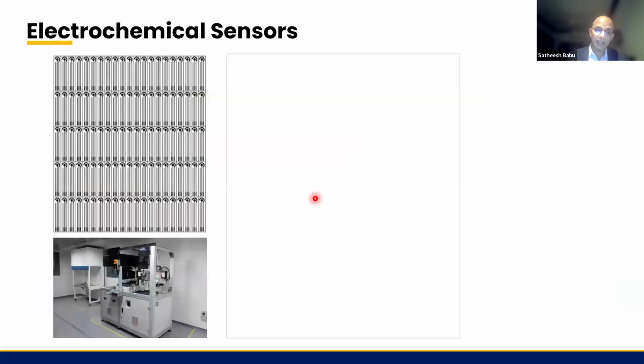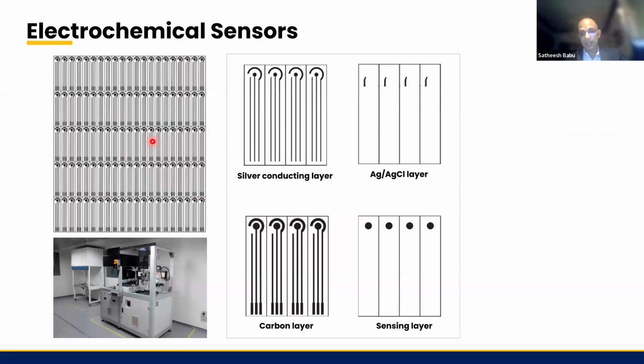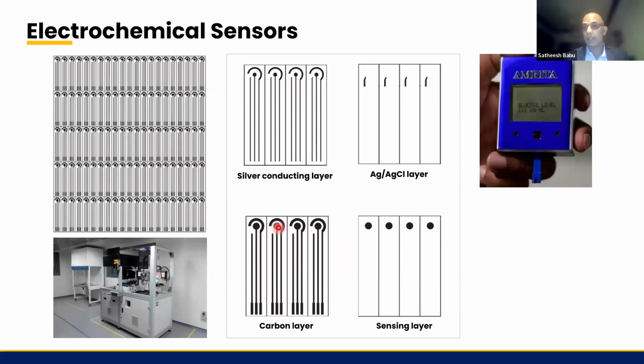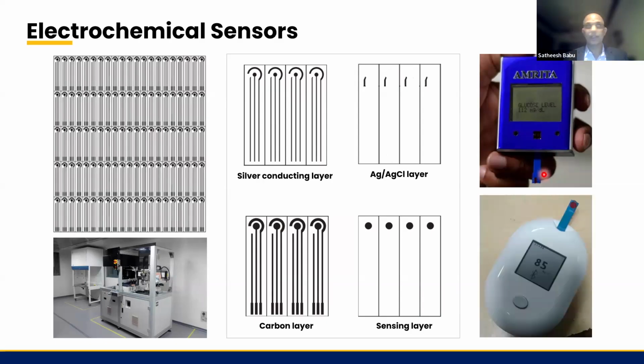Then slowly we translated the same thing using printed electrodes. We have an automated printing system with which we could print the electrodes as everyone does, like a silver layer printed to enhance the conductivity. On top of it, we printed the carbon, and we printed the silver chloride reference electrode. Then the catalytic material was also printed on the working electrode. Then the indigenously developed glucometer, we were able to connect with this, and we could read the sensing.